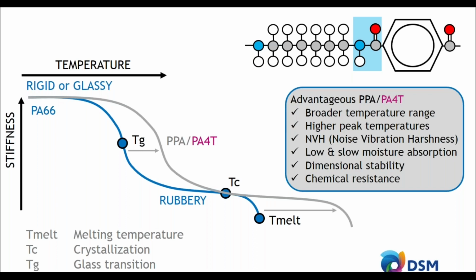PPAs also show a much lower and slower moisture absorption. That means the strength and stiffness are not as much influenced by moisture as with a polyamide 6,6. A polyamide 6,6 can absorb the maximum amount of moisture in around 1 to 2 weeks, and a PPA takes over half a year to absorb that amount. That also means that the dimensional stability of a PPA is in general higher than for a polyamide 6,6.